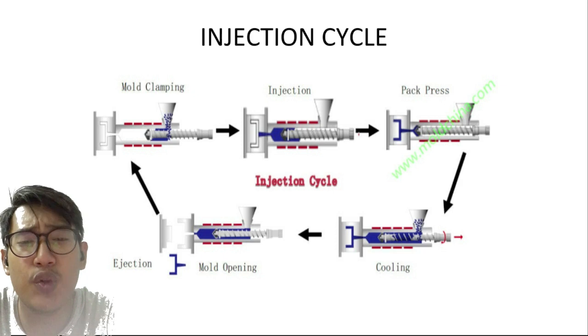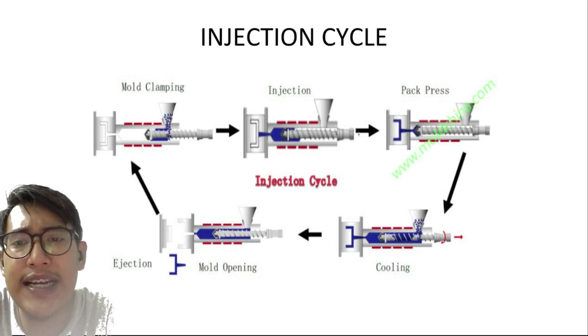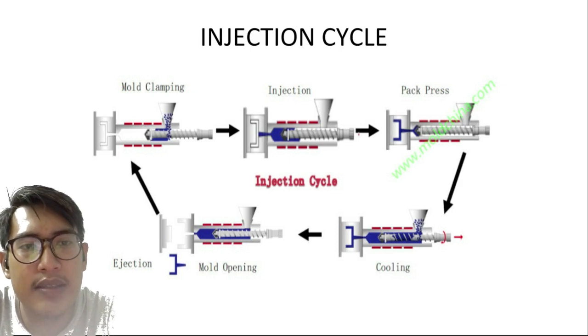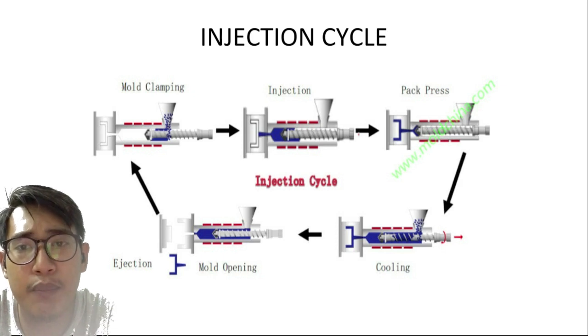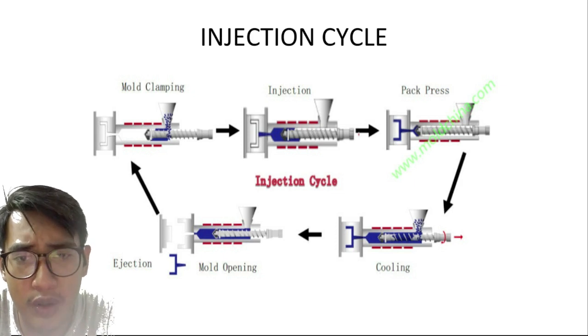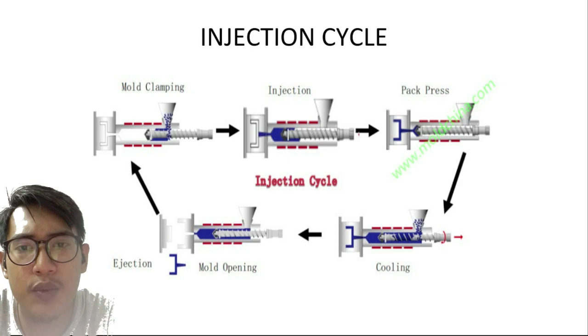It is important to completely fill the mold and avoid overpacking or underpacking, since packing pressure determines part weight and part dimension. Overpacking can cause dimensional problems and difficulty in ejecting the part, while underpacking can result in short shots, sink marks, part weight variation and warpage.